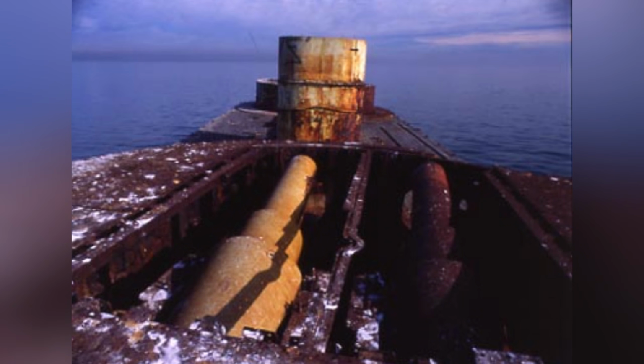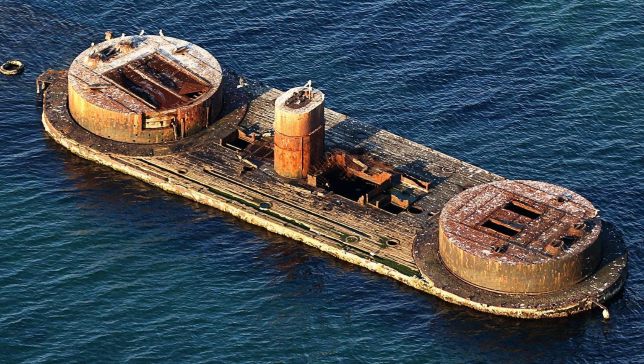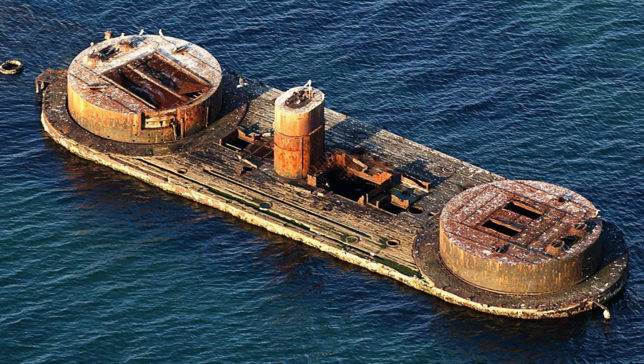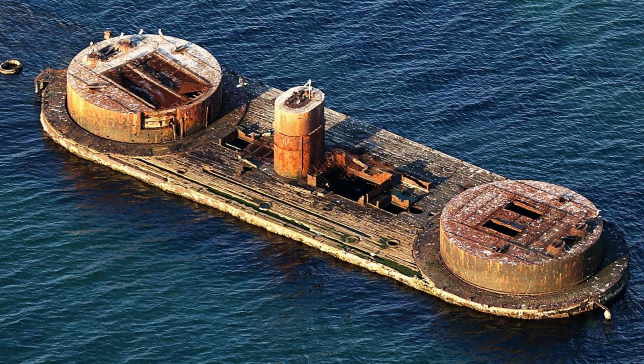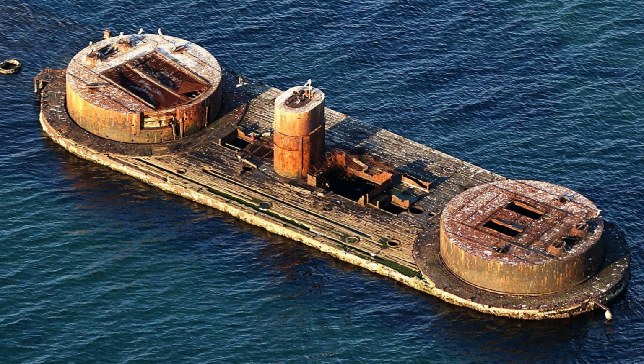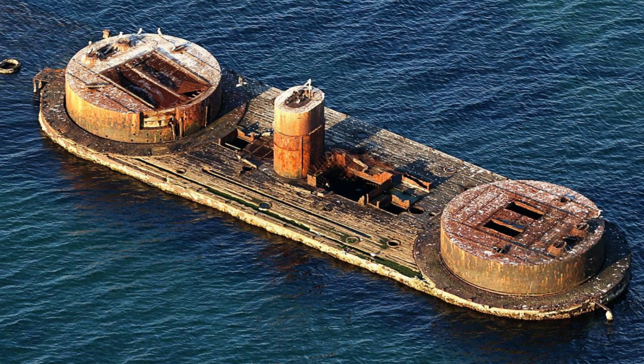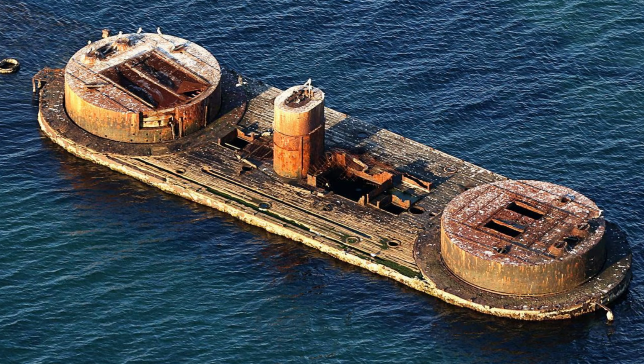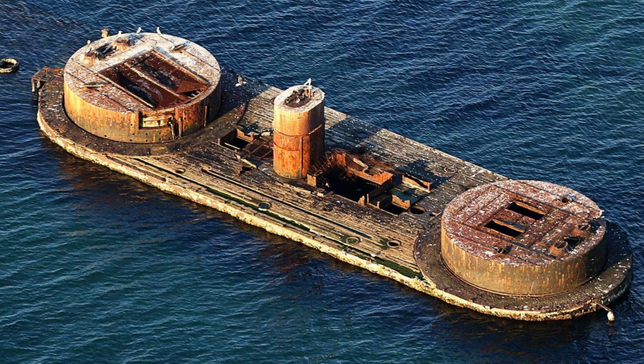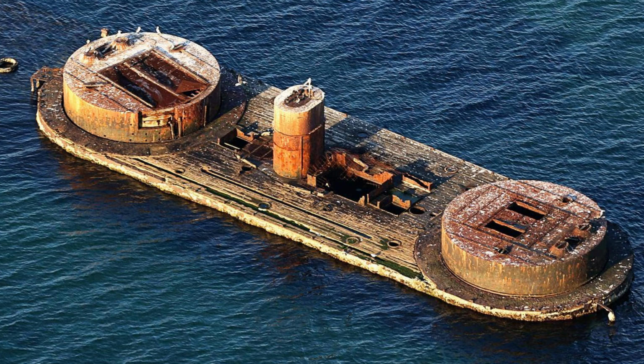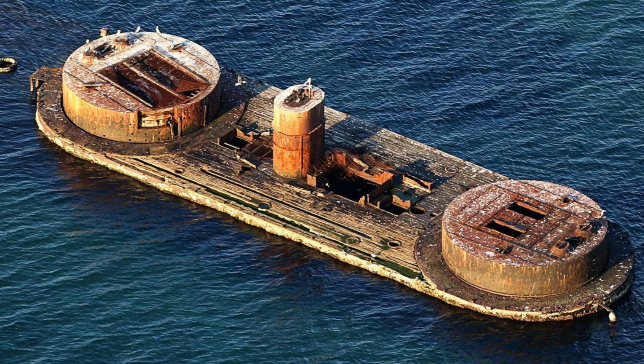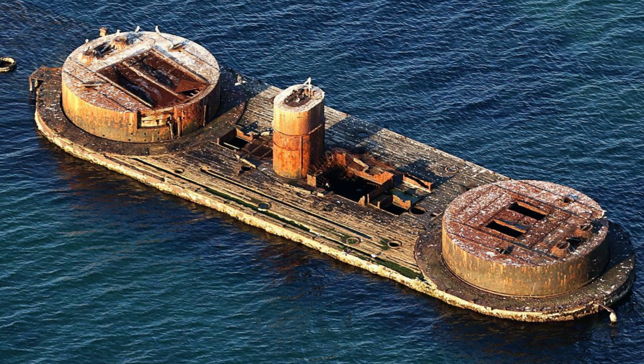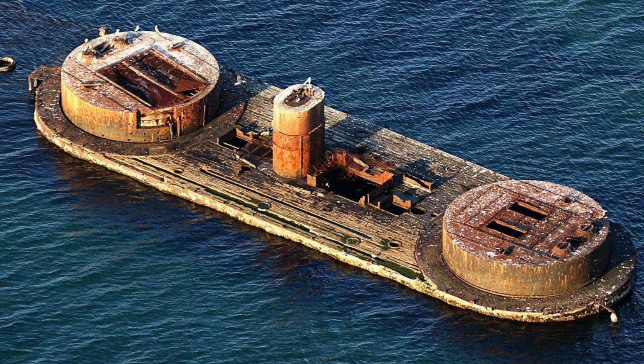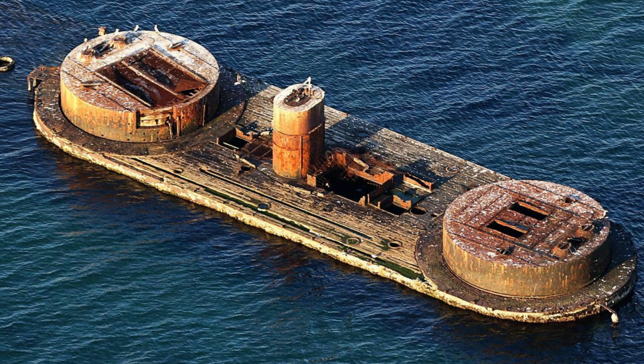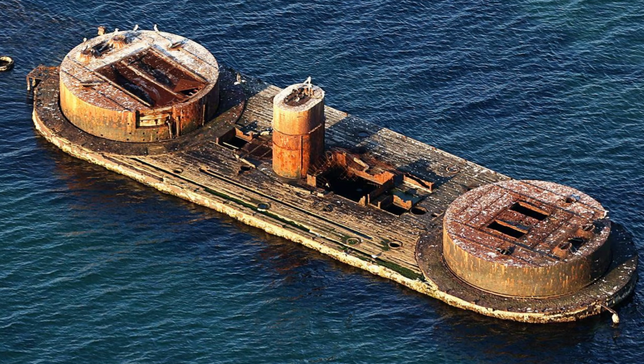The preferred stabilization concept was blunt, practical, and scalable. Build a low protective wall around the wreck's base, then fill the interior with dredged sand so the turrets and surviving superstructure would be supported by the ground beneath, not by rotting ironwork. But even a successful stabilization would establish a hard limit. A full restoration or complete recovery would remain unlikely without a major, purpose-built project and sustained funding. The lower, unarmored iron has already suffered severe loss, and ongoing corrosion is expected to continue.